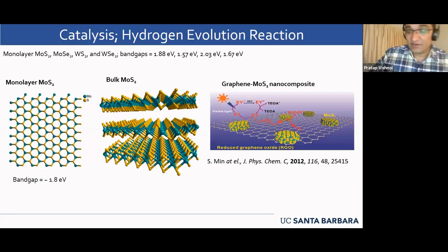What the reason is, let me tell you. Graphene, when it forms bands, the VBM and CBM, they don't have a gap. They're actually talking to each other. They're touching each other. So basically, electrons in VBM and electrons in CBM have no energy difference. They're the same. So it cannot do that. And such types of materials are also called semi-metals. They are not called semiconductors or insulators. They are not metals, but they are also not semiconductors, so semi-metal.